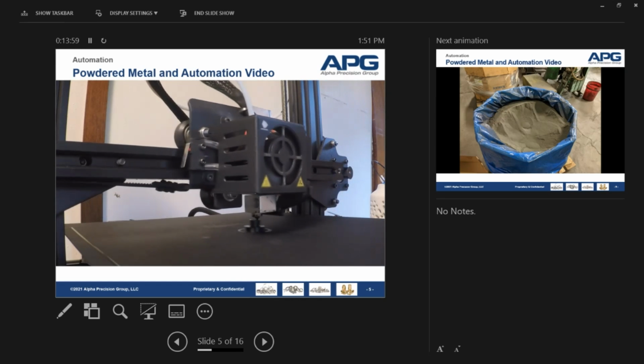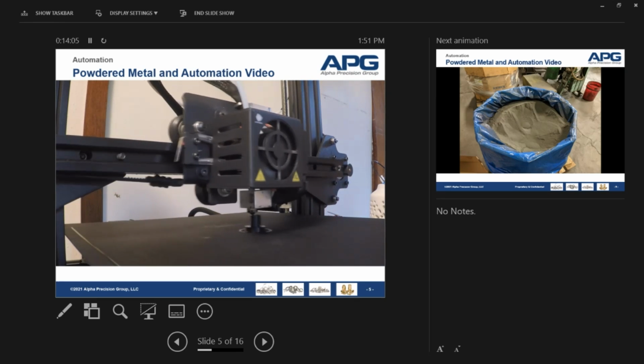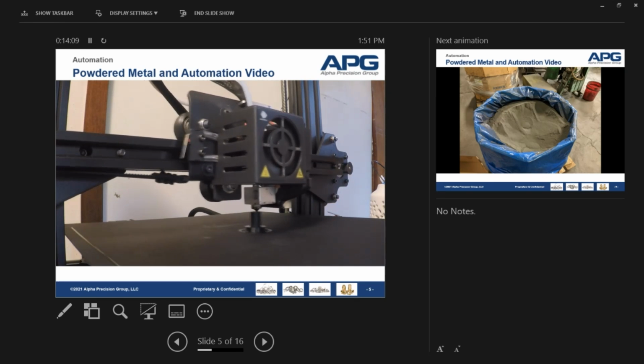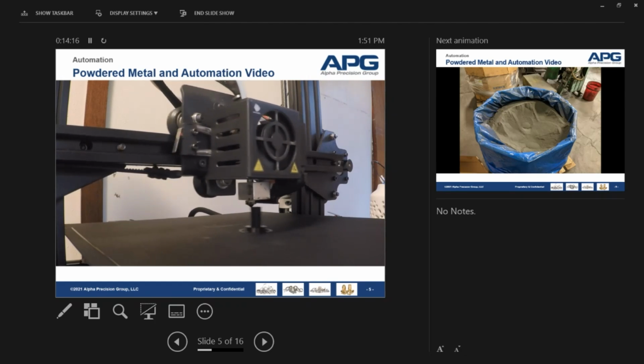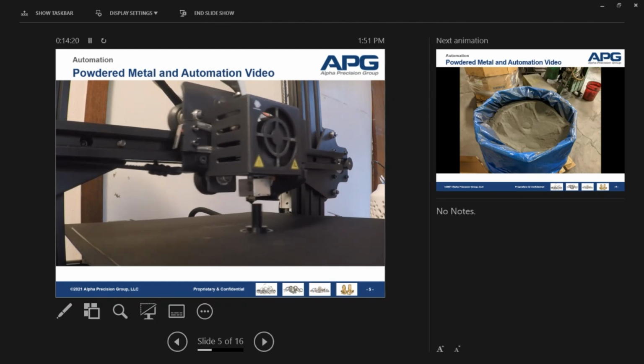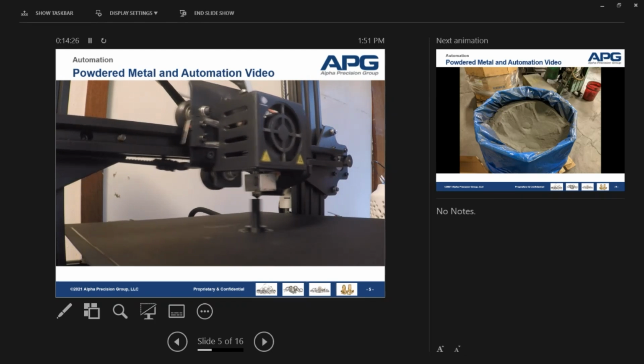And this particular printer, the piece that it's on, that black sheet right there, is even a heated bed that'll get heated up to about 100 degrees Celsius. Keep that part on there while it's printing, and that hot end, that silver piece that it's printing out of, goes to about 210 degrees Celsius to melt the filament. And like the slicer said, this took probably about 27 minutes to print, and the very next day I have a working piece that I can use.